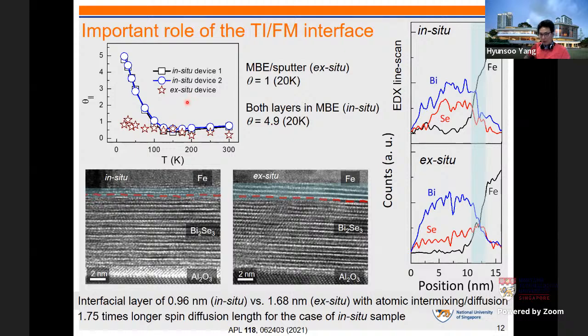We also used the ex situ method, meaning we grow bismuth selenide in the MBE chamber, take it out, and then put it in a sputter chamber, so there is an exposure to air. And you can see in that case, the increment is very moderate and a similar value across all these temperatures. So basically, they indicate that depending on the fabrication method, it can have very different temperature dependence. So we looked at those using TEM and also EDX scanning of the profile, and we found that there is an intermixing layer and also a diffusion layer at the interface, which is always the case in a heterogeneous growth.